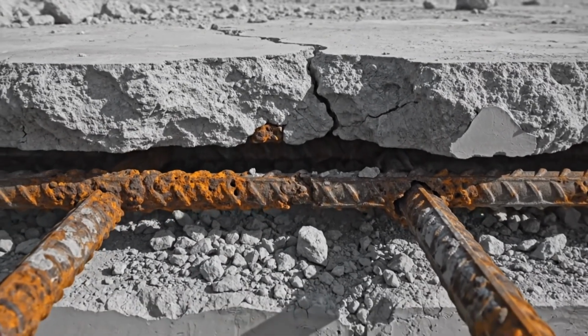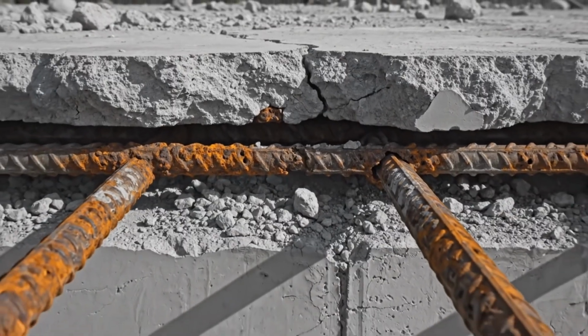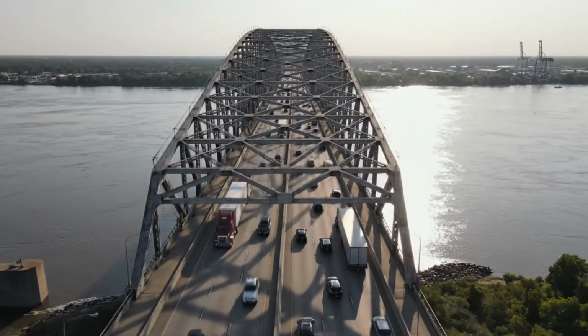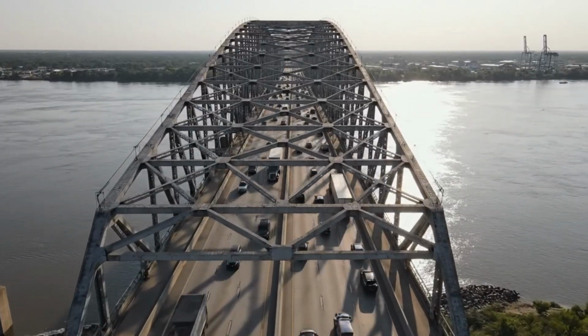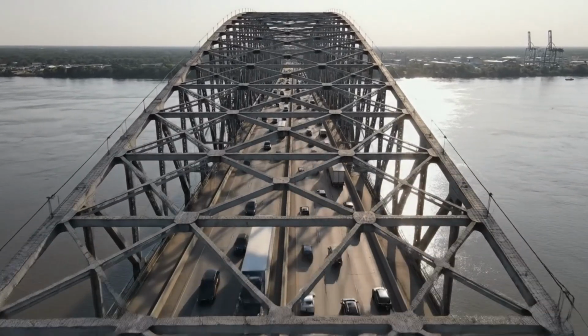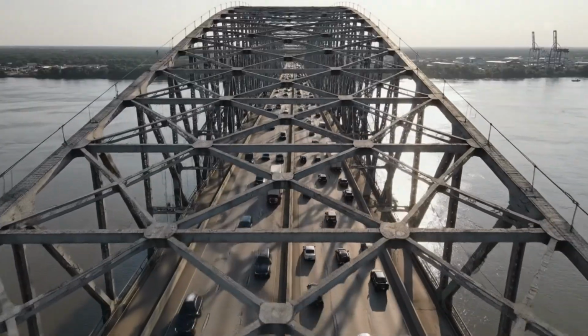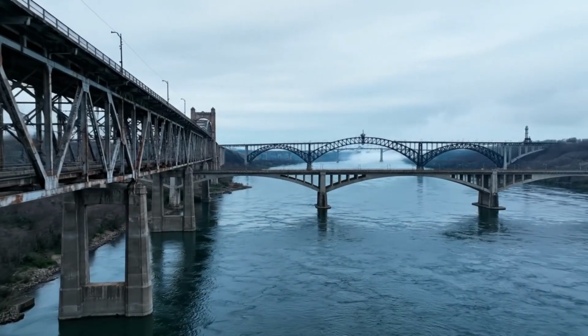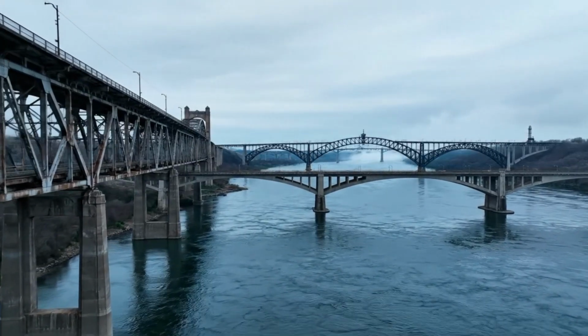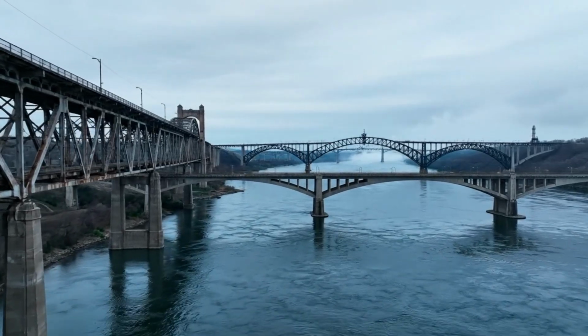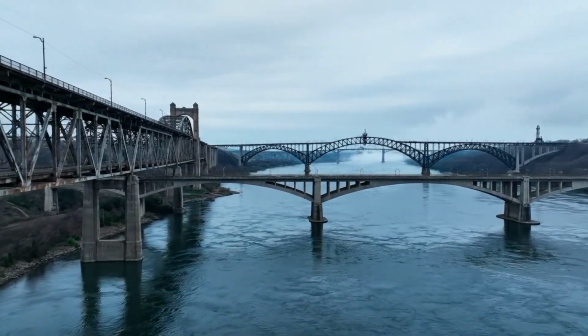It looks innocuous, a faint brown discoloration, often mistaken for mineral staining or runoff, bleeding through the gray concrete along a line that follows the exact path of the embedded rebar below. By the time it appears, the rebar has lost measurable cross-section. By the time the first crack opens along the stain line, expansive corrosion force has exceeded the concrete's tensile capacity. By the time a chunk of cover detaches, revealing rust-brown rebar, structural capacity is permanently reduced.